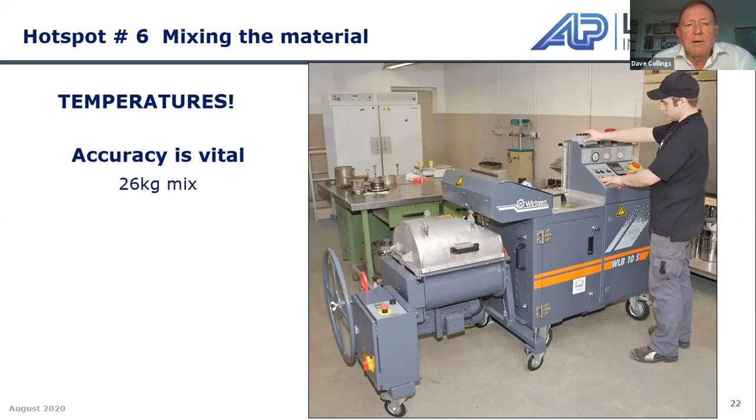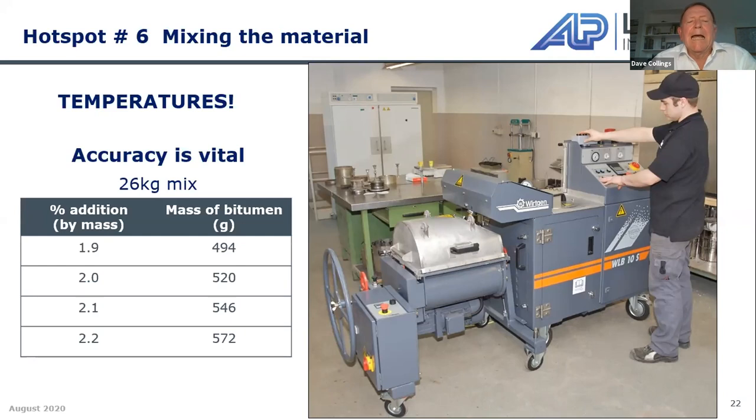This is critical, okay? If you've got a 26 kilogram mix, and you want to add different amounts of bitumen to different samples, the difference between the amount of bitumen you're adding is really small. But this is where the money is. And this is why you need to be able to do these tests at precise bitumen additions and then use those in your mix designs and use it on site. Just remember,